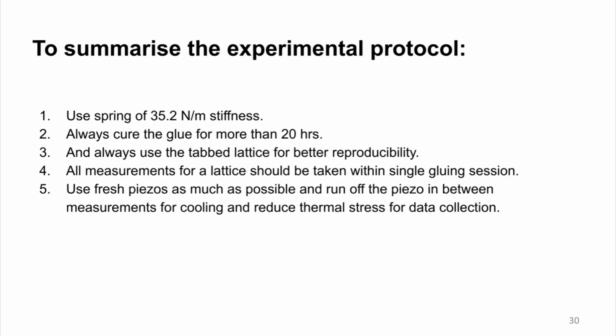Also, I use lattices with placement tabs, and that helps me achieve reproducibility and avoid inconsistency of placement of the piezoelectric every time I take a measurement. And lastly, I use as much fresh piezos as possible and allow cooling time in between measurements to reduce any thermal stress on the piezoelectric.